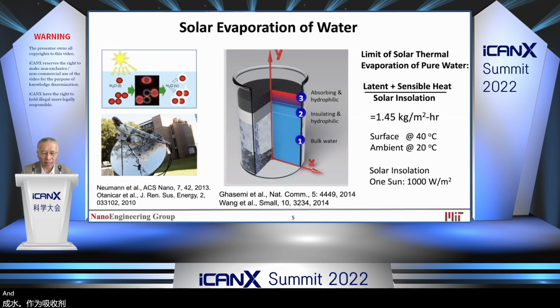And about 8 years ago, we thought about another way. Let's float some absorbing material, in this case really a carbon foam, on water. It's porous, so you can suck up water through surface tension, and the solar energy can focus on the surface. In that case, only the surface gets hot, and the rest of the water stays cold. So you can get quite efficient solar evaporation of water.